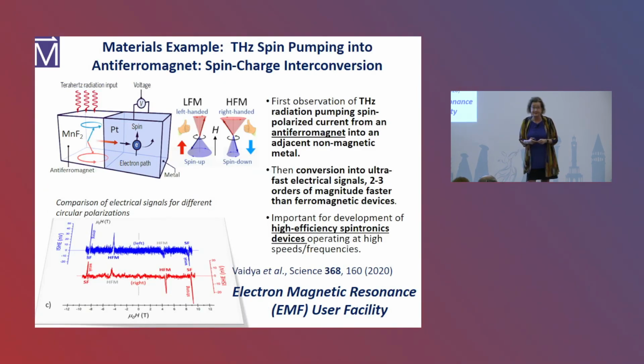This one I'm glad I threw in here because Ahmet might be interested in this. So this is all still prototype. This is some of the spin transport they were doing on our electron magnetic resonance area. So this is EMR. They also call it electron paramagnetic resonance, depending on where you've been. But what we have here is an antiferromagnet that's attached to a non-magnet, okay? So this is a heavy metal, platinum, manganese difluoride, and you send in terahertz radiation, and you get a spin transport across, and you can bring out ultra-fast electrical signals. So it's spin transport through this platinum.